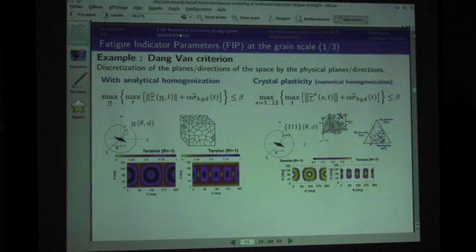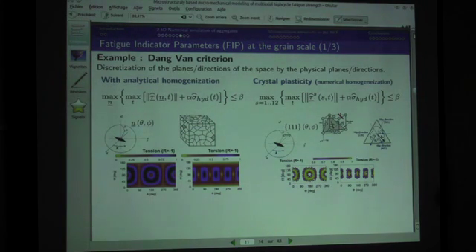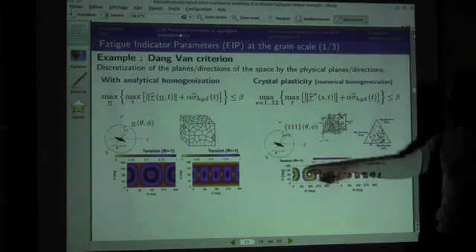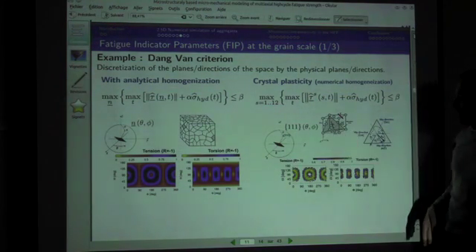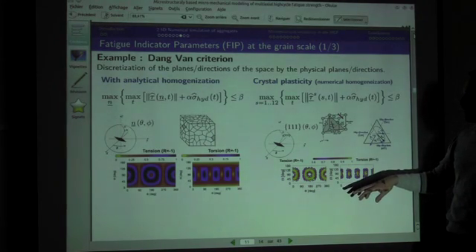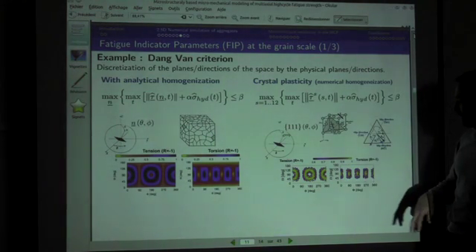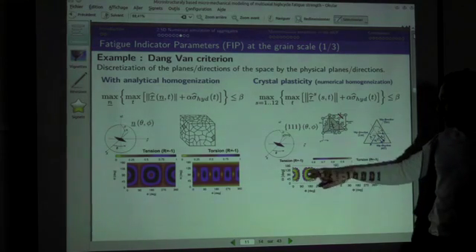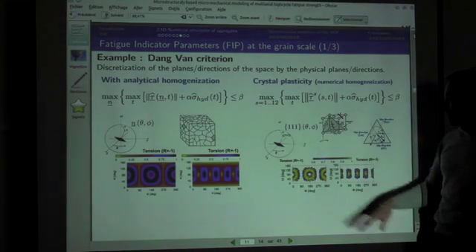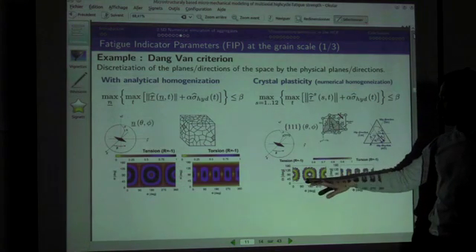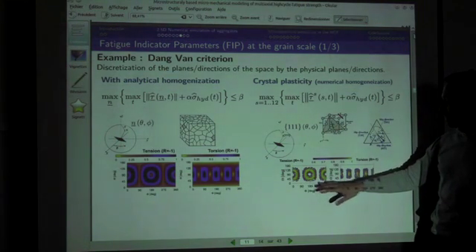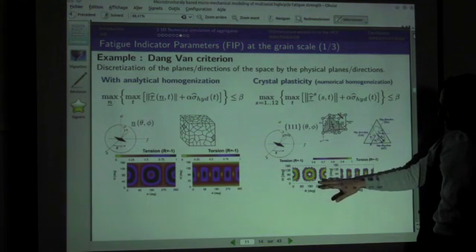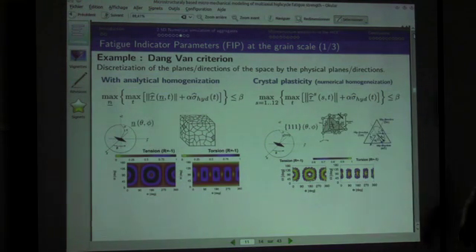just because we consider that crack initiation is related to the development of plasticity at the grain scale, and then we have a crack, slip to crack transition, but on the slip system of the aggregate. And if you do this, and you look at the distribution in space for given loading of this parameter, of the criteria here, of Dang Van parameter, you will see that it changes quite a bit the picture between the continuous in terms of space to the when you go to the discrete analysis in the space with respect to the slip system of the aggregates.